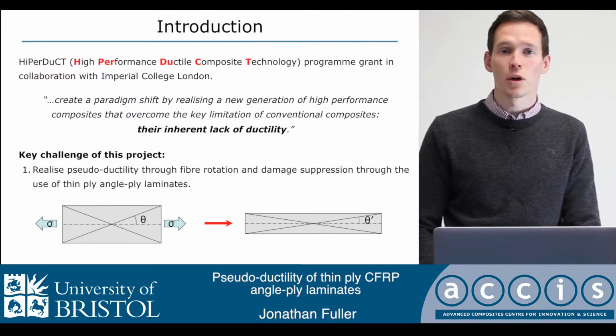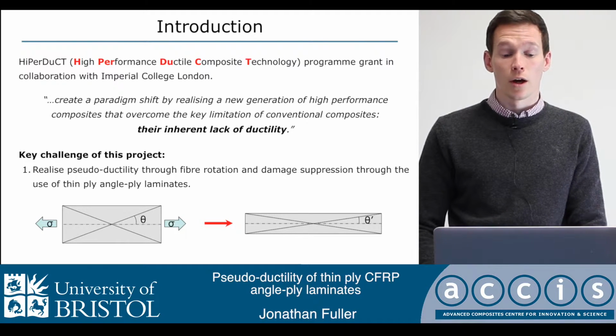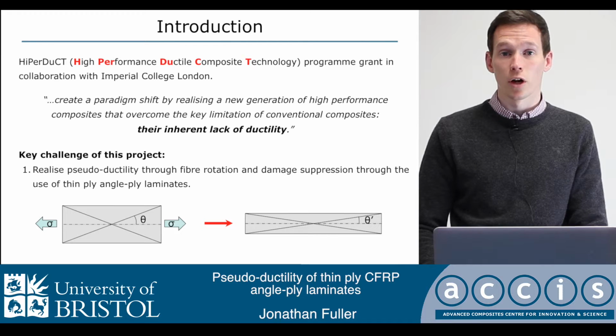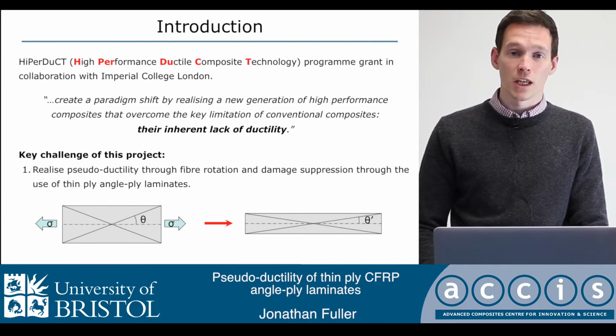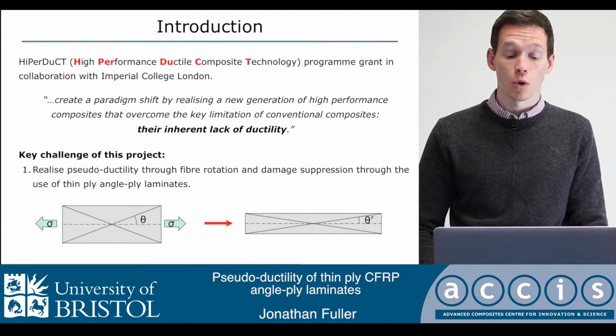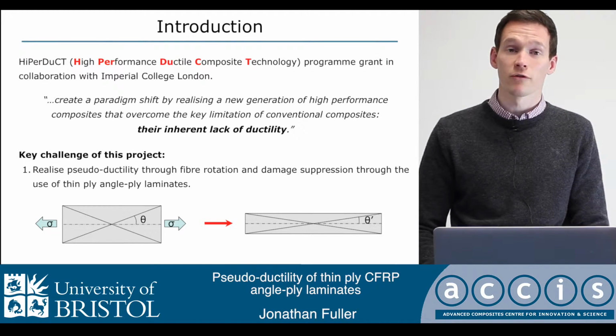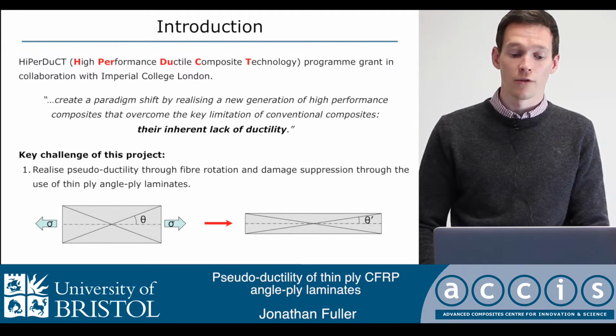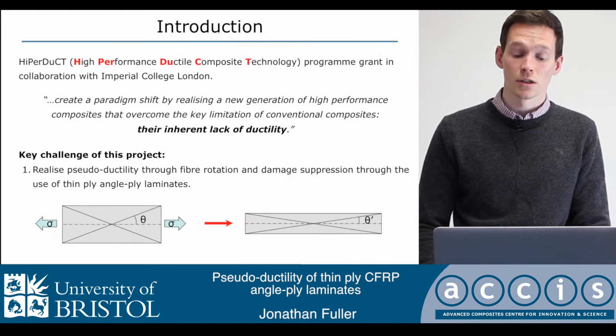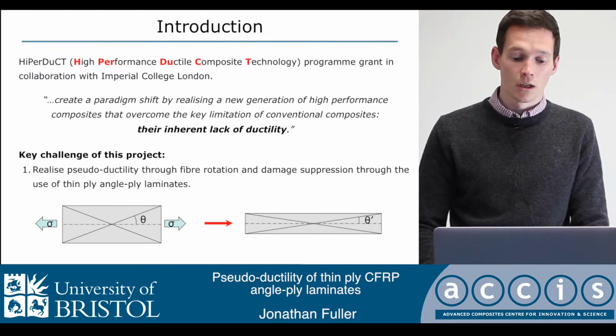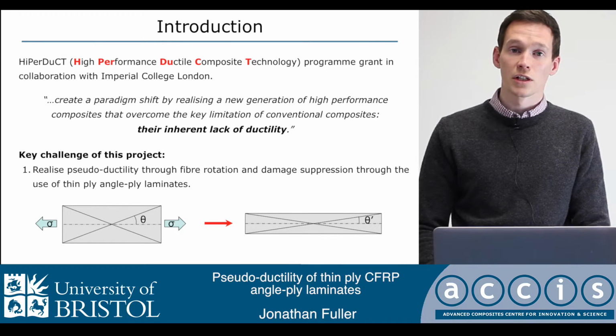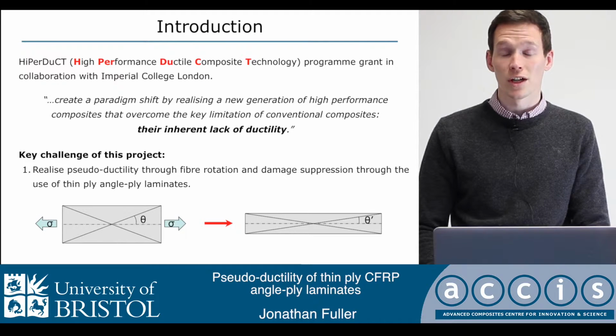To introduce, this work has been part of the HiPerDuCT, High Performance Ductile Composite Technology Programme grant, which is collaborative work with us and Imperial College. The key aim of this work has been to create a paradigm shift by realizing a new generation of high-performance composites that overcome the key limitation of conventional composites, their inherent lack of ductility. My work, this project, has been looking at pseudo-ductility through fiber rotation and damage suppression in thin-ply angle-ply laminates.